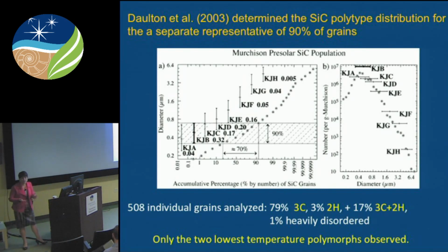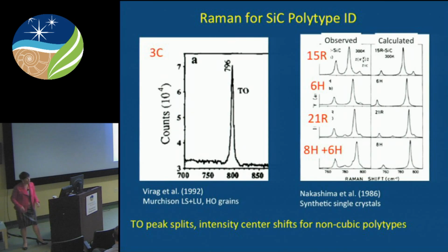But in his analysis of over 500 grains, he found that nearly 80% of them were the same 3C silicon carbide form. A minority were the hexagonal, and sometimes some intergrowth. But none of the 4H and the 6H that we like to grow in the laboratory for the wide band gap properties.